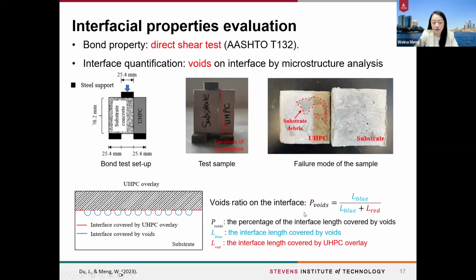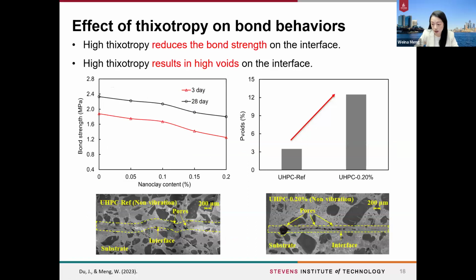And we also evaluate the interfacial properties of the UHPC and the substrate concrete. We use the direct shear test to evaluate the bond strength at this interface, and we also quantify the voids at the interface by microstructural analysis. The result shows that increasing the thixotropy by increasing the nanoclay content would reduce the bond strength. This is because more air voids were introduced at the interface.